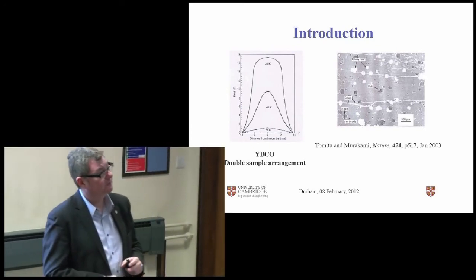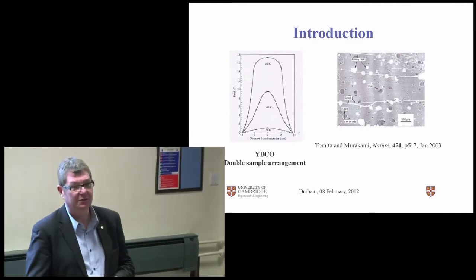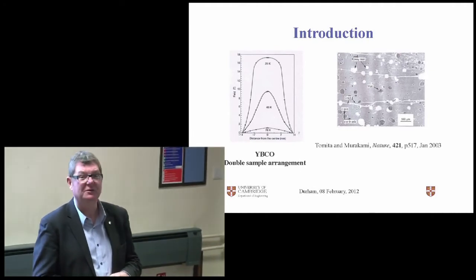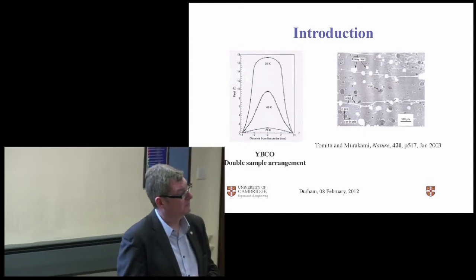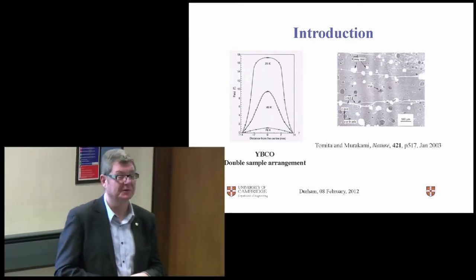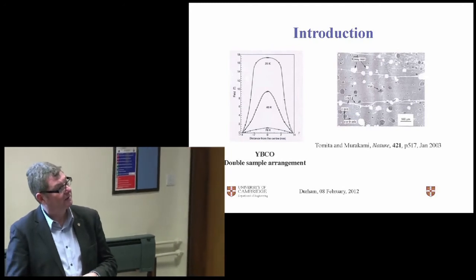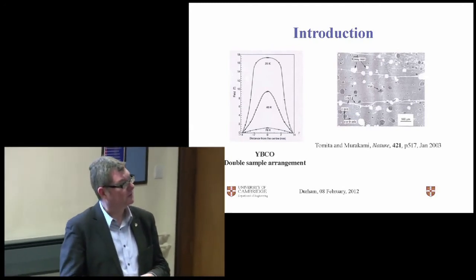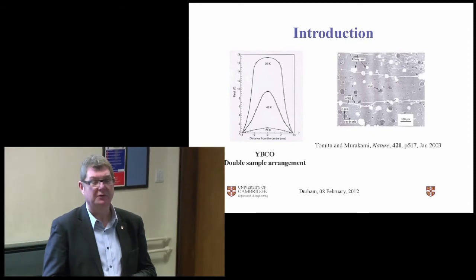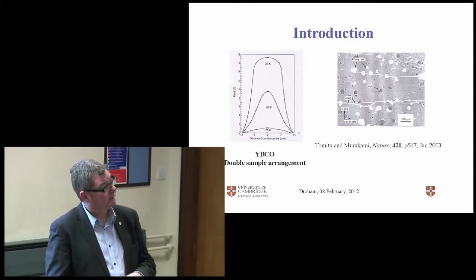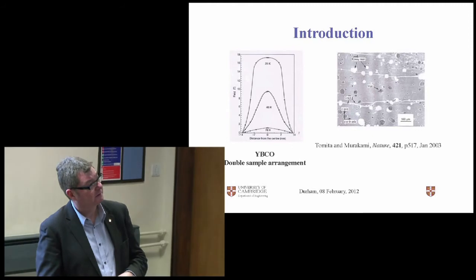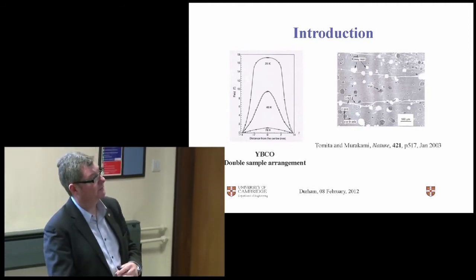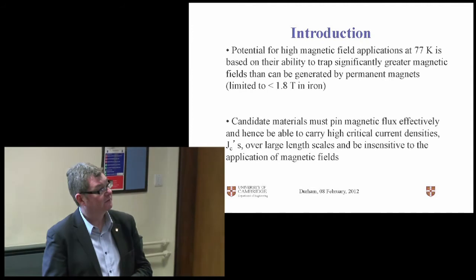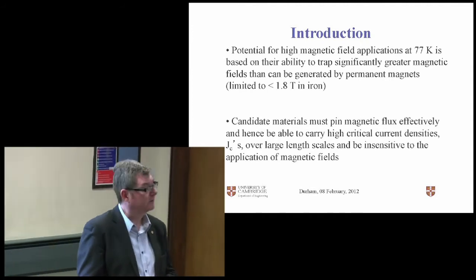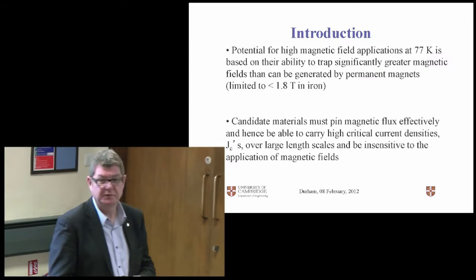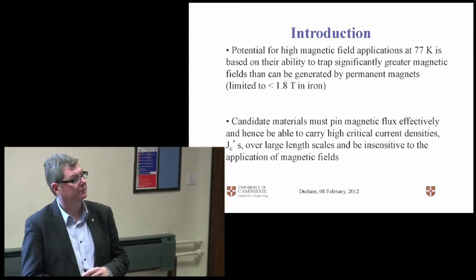I feel compelled to show this cross-section of the material from the same sample. It looks absolutely horrible. From a purist point of view, and I'm a bit hesitant in the Department of Physics in pointing this out, but in terms of symmetry and long-range order, it's got nothing going for it. However, these microcracks don't carry current in this direction. Current flows out of the board and back in and generates an actual field as we're showing here. So one argument is that if you're applying this and it's going to support a field for a long time, who cares what the microstructure looks like?